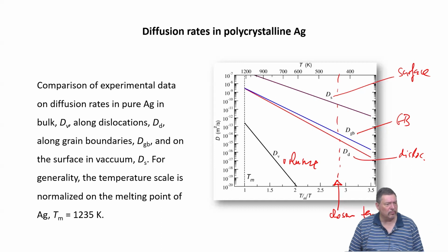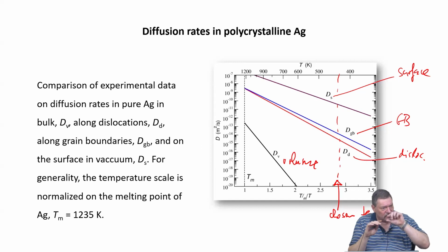It's just too slow. You might encounter dislocation pipe diffusion and grain boundary diffusion. And surface diffusion we take out because we cut the outer surface. So whatever diffused we cannot prevent, but we take out a sufficiently thick part of the outer surface of the sample so that it's no longer affecting our measurement when we put the slices into a detector to count the radioactive